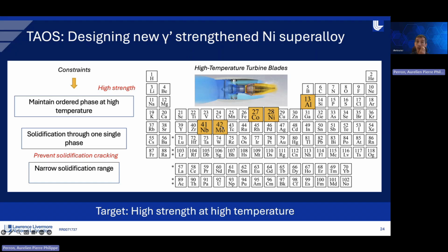And so what are you going after for a superalloy? You want to have an ordered phase at high temperature, so gamma prime, to give strength to your alloy. But because of your process, you also want to minimize cracking. So for that, you want to solidify your alloy through one phase, mainly FCC at the end of solidification, and you want to have a narrow solidification range. That's the state where the alloy has both liquid and solid phases.